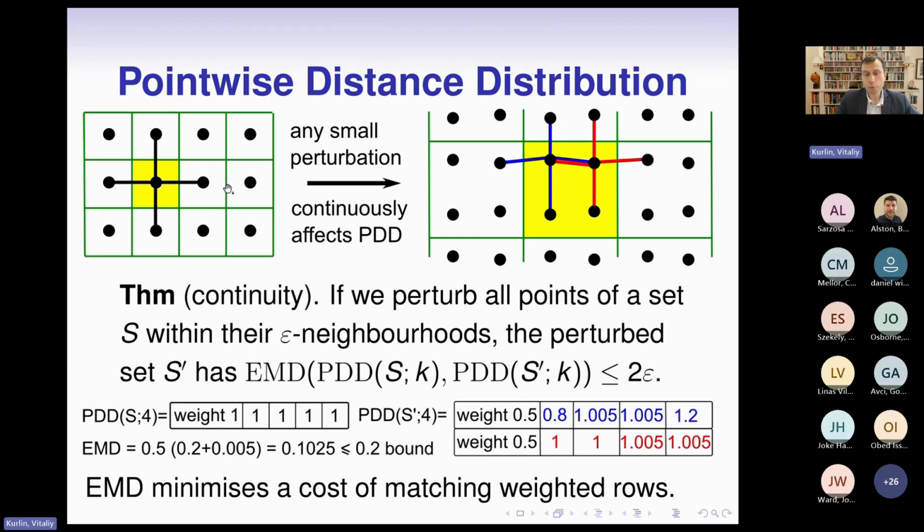But under small perturbation, our unit cell can change. So this is a small perturbation chosen to make all numbers simple. We can easily get a 4 times larger unit cell. However, distances actually changed only a little bit. So I pushed up one point by 0.1 and this point down by 0.1, so that the distance now between them is 1.2. So this number appears here. And the smallest distance now becomes 0.8 for simplicity. So as you see, all distances changed only a little bit. So they depend on this small perturbation epsilon.